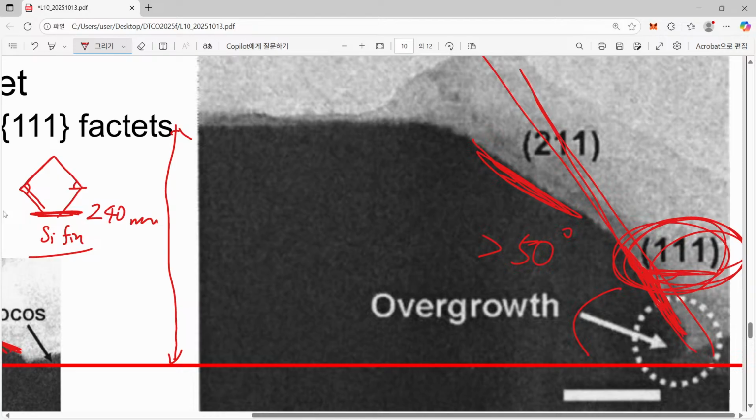So that's the reason why we have a typical diamond structure. Then why do we have this diamond structure, and what is the magic behind it? It is critically important for FinFET because the source drain resistance is largely given by the shape of our diamond structure.